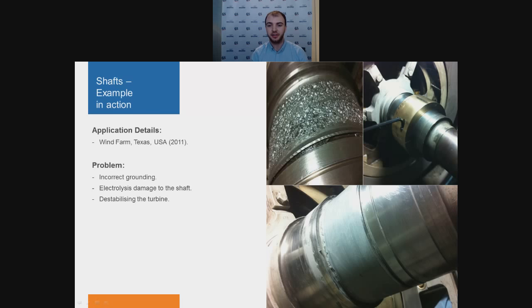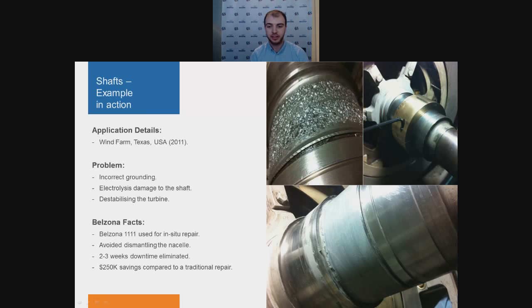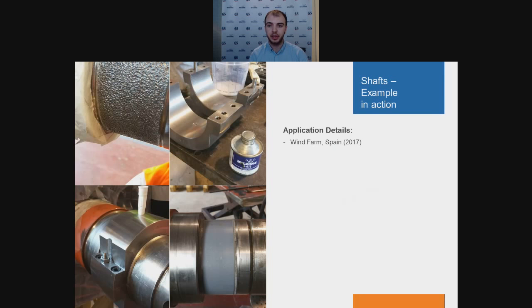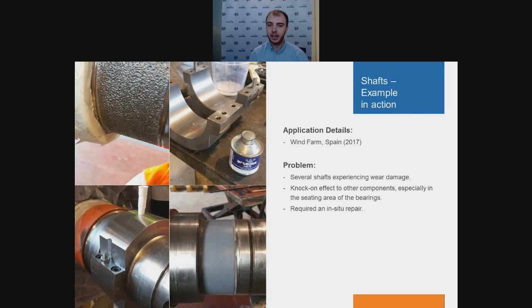However, overall, this would have led to 2 to 3 weeks of downtime and significant cost implications as a result. So, the client used Belzona 1111 and repaired the shaft in situ. Due to the cold curing properties and easy application of this material, dismantling the nacelle was avoided, and approximately $250,000 worth of savings were noted with this simple repair option. In this instance, the customer had the ability to bring the equipment down for much needed maintenance. Rather than employing any hazardous hot work, Belzona was applied via injection, and what the client did afterwards is they used several different